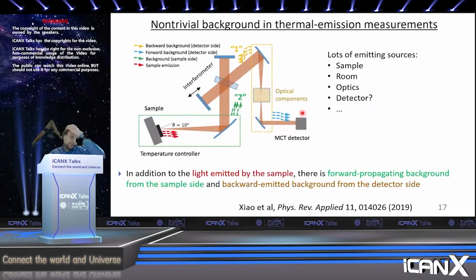And what we found out afterward, and I'll show you how we came to that conclusion, is that we have a non-trivial background in our thermal radiation measurements that's going in the opposite direction in our Fourier transform spectrometer. So here's how this experiment is done. We have a sample, we have a temperature stage, the sample is tilted for technical reasons, but that doesn't matter too much. We have this Michelson interferometer with a moving mirror. This is what's called a Fourier transform spectrometer, or an FTIR. And we have a detector over here.